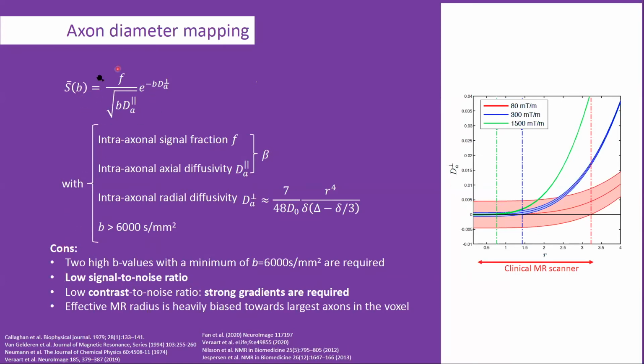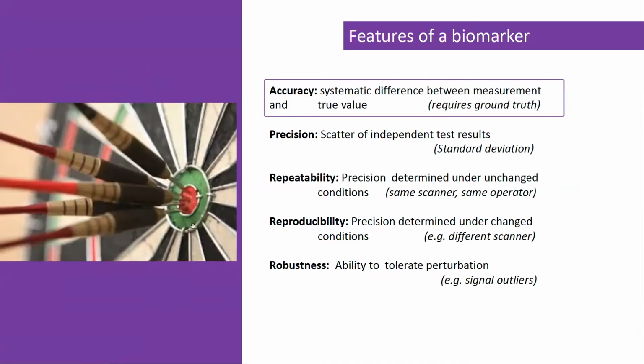The problems of the model, or the limitations of the model: we need two very high b-values with a minimum of b 6000 to solve it. We will always have to deal with a low signal-to-noise ratio, and there's a low contrast-to-noise ratio, and strong gradients are really required. And even if we can deal with those three, we only measure the effective MR radius, which is heavily biased towards the largest axons in the voxels, which might limit its application.